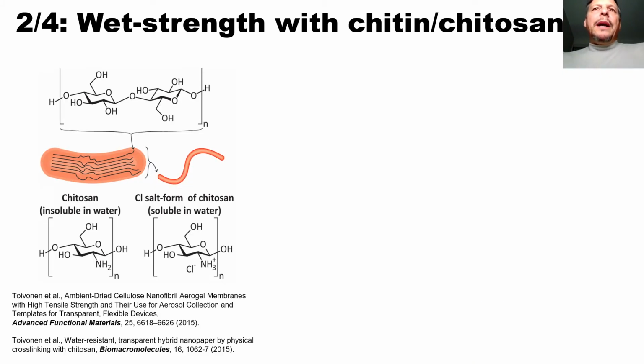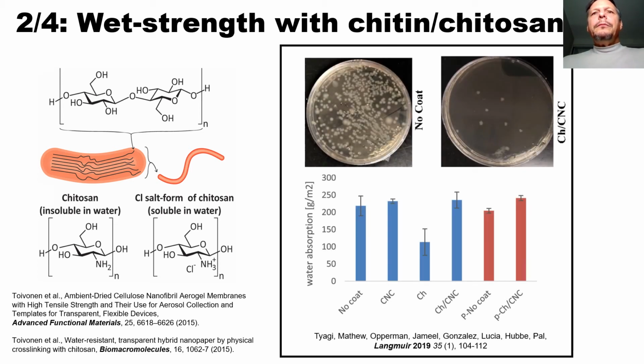Another example of the bulk addition of chitosan is the possibility that chitosan can form complexes with cellulose, especially if cellulose is oxidized. And that will produce materials that display very high wet strength. Also of particular value is that besides the wet strength that develops, antibacterial properties can also be seen. My colleague Lokendra will be talking about this topic. In this particular case, I think it's important to mention that we can either use the chitosan in the bulk, or as was proposed in his group, the idea of using chitosan together with cellulose nanocrystals as a material that can be sprayed on top of the tissue paper to reduce or avoid or limit at least the bacterial growth.